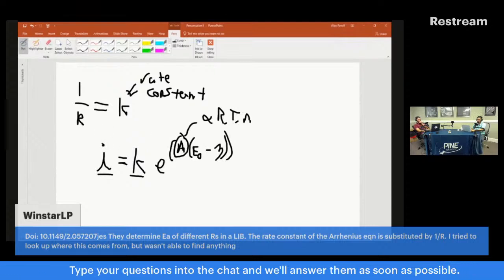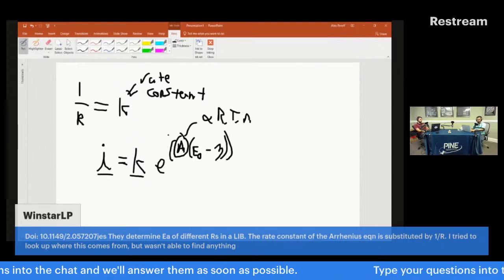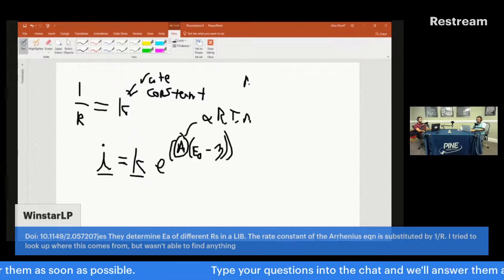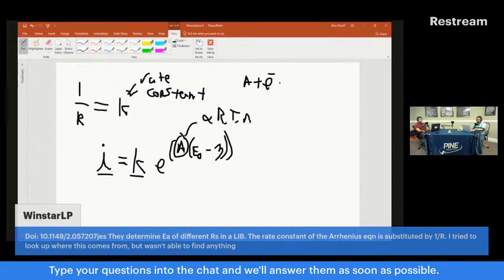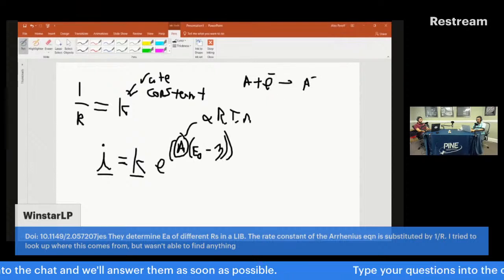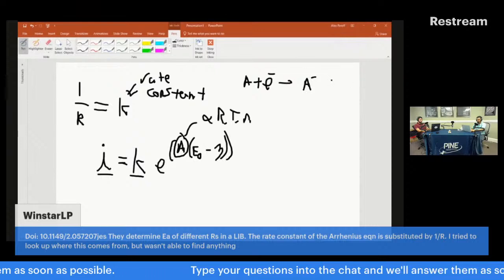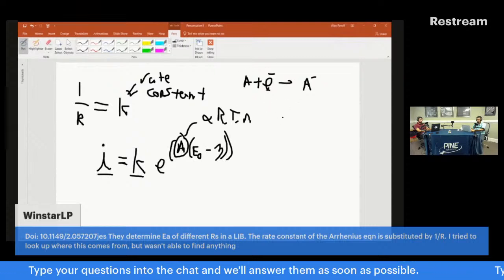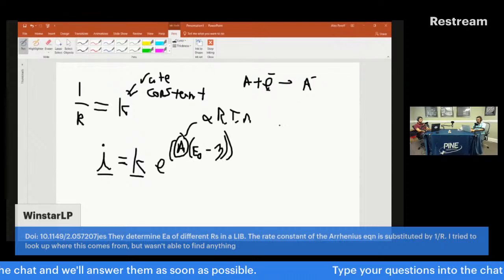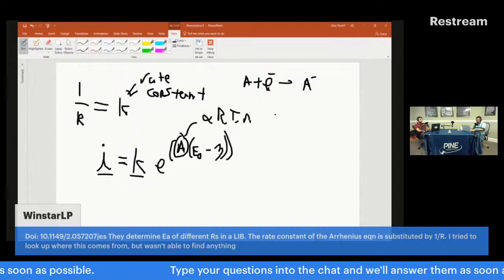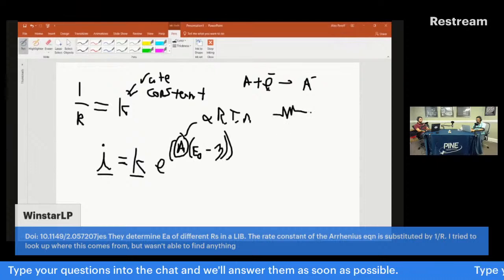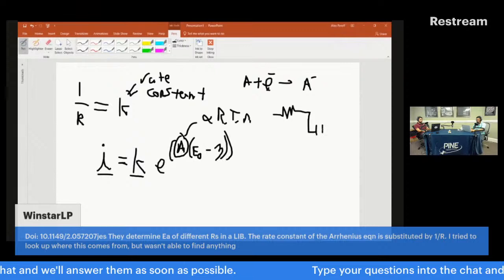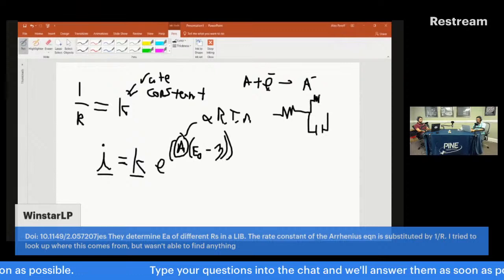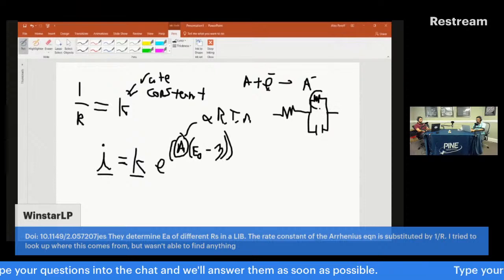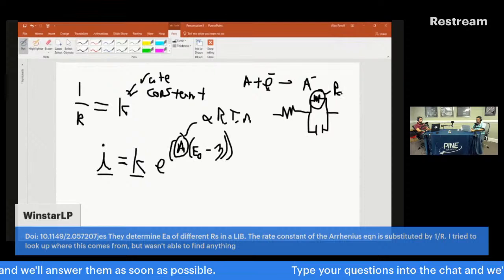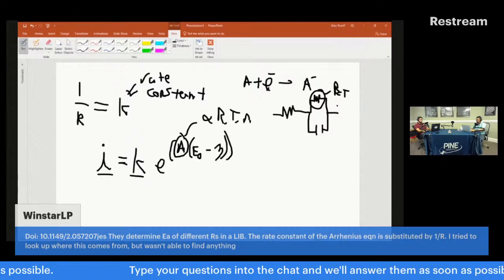And what people can do is, now this equation has to do with an electron transfer reaction, right? This has some kind of A plus an electron gives you, let's just call it A minus, right? So you have your oxidized and reduced form. So it's an electron transfer reaction, which means that when you're looking at a 3-electrode system, working electrode, we model it in impedance as the solution resistance, a Randles circuit. You have double layer capacitance, and then you have your charge transfer resistance. And this charge transfer resistance is a resistor, RCT.